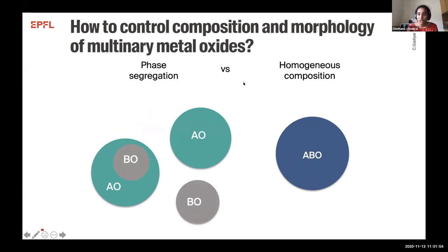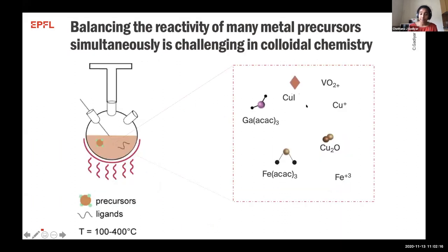And the composition and morphology of these multinary metal oxides are very important because they control the performance of these materials. From a synthetic point of view, it's very difficult to control this composition and morphology because there's always a competition between phase segregation versus formation of homogeneous composition. And this is especially challenging in the case of colloidal chemistry, because when we have ternary oxides forming, there's always a competition, and there needs to be a balance in reactivity of the different precursors that we are using. So this is quite challenging in the case of colloidal chemistry.